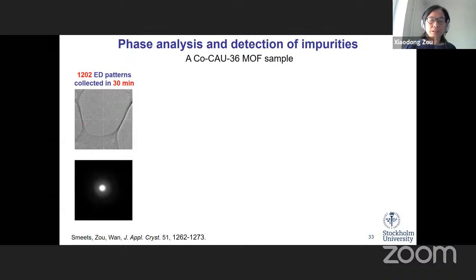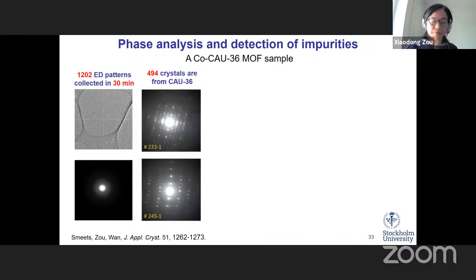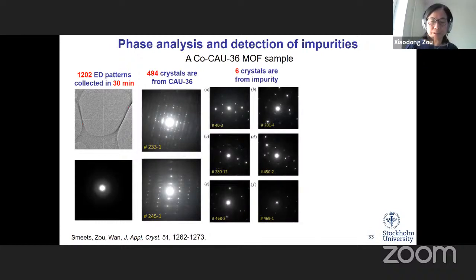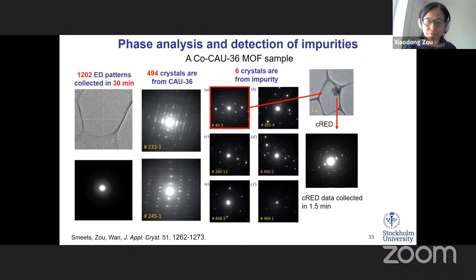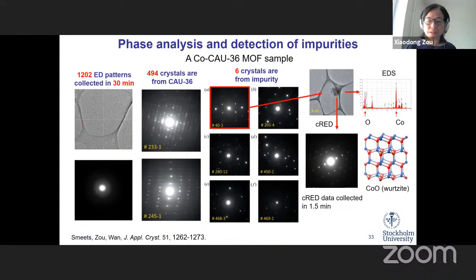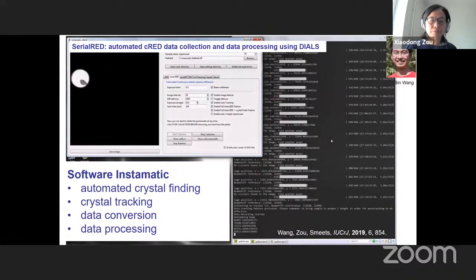And with this technique, it is now possible to find not only the phases we wanted and use them for the structure determination, but we can also find the impurities in the crystal, which cannot be observed using powder X-ray diffraction, for example. In this case, out of 1,200 electron diffraction patterns, we found 6 diffraction patterns that are different from the main phase. And from these, you can collect electron diffraction data and find out what this phase corresponds to. And using this technique, we could detect many new materials that were not seen by X-ray powder diffraction. So this is a very good, unique application.